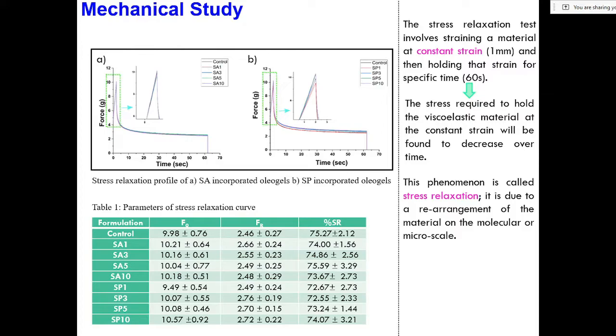Then we performed the mechanical study. We performed the stress relaxation study to analyze the mechanical properties of the oleogels. We did not find any specific changes in the mechanical properties. Okay, this was important because we want to alter the thermal properties of the oleogels without compromising the mechanical stability or the oil binding capacity of the systems.